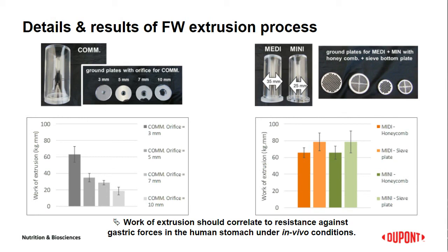In this slide, we have first used the commercially available setup, which is given on the left side of the slide. Four different ground plates are available for the setup, and the investigated work of extrusion decreases with increasing hole diameter. The commercially available extrusion tube had a diameter of 50 millimeters, and in order to extend the extrusion process, we have constructed two new prototypes with 35 or 25 millimeters called MIDI and Mini extrusion cell. As bottom plates, we have used two different setups for both, one honeycomb structure and one sieve bottom plate. The obtained work of extrusion of the new prototype geometries showed increased reproducibility.